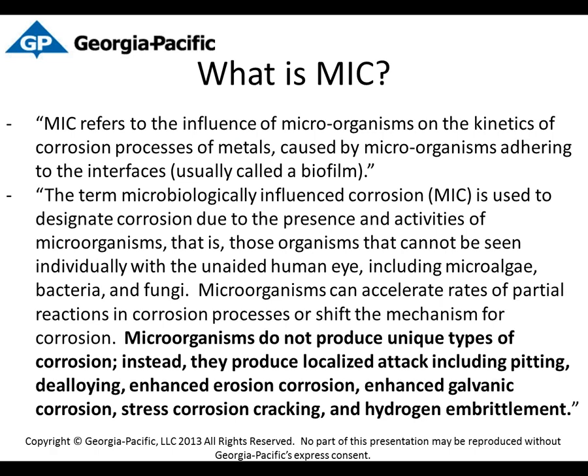So the term microbially influenced corrosion is used to designate corrosion due to the presence and activities of microorganisms. That is, those organisms that cannot be seen individually with the unaided human eye, including microalgae, bacteria, and fungi. Microorganisms can accelerate rates of partial reactions in corrosion processes or shift the mechanism for corrosion. So like I said, these organisms in and of themselves don't eat the metal. They just accelerate rates of partial reactions. They can accelerate the anodic reaction or the cathodic reaction. One of those cathodic reactions we saw was hydrogen evolution. So some microbes, like methanogens, will actually take that hydrogen and pull it away from the surface to allow the rate of the cathodic reaction to increase, and that can drive the corrosion reaction faster.